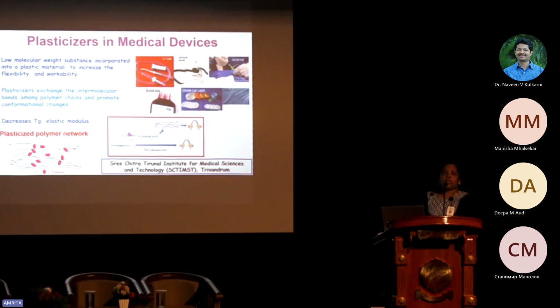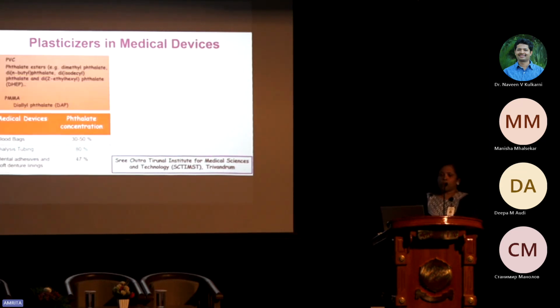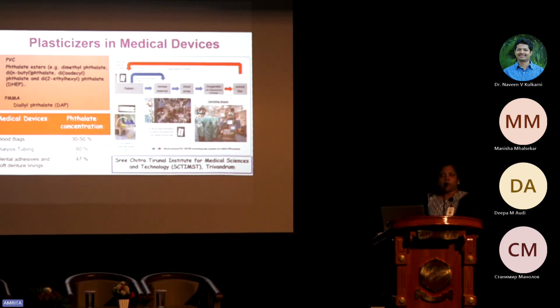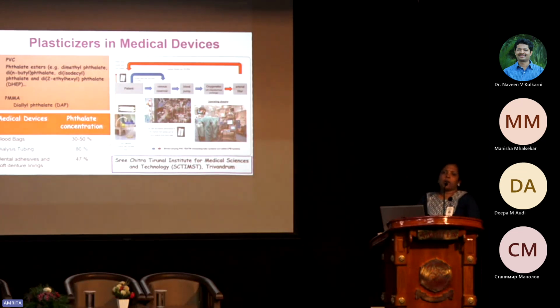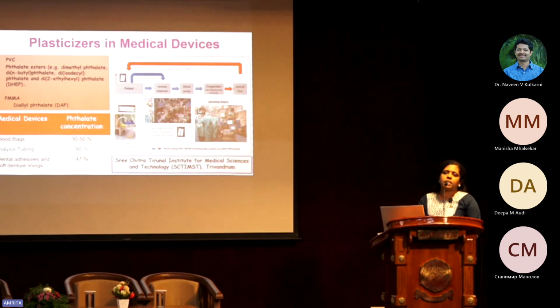So the plasticizers are used in many biomedical devices, including IV tubes, catheters, blood bags, etc., and also in very high concentrations. There are different forms of plasticizers used depending upon the polymer matrix, the parent polymer matrix, and also the application. In PVC, that is polyvinyl chloride, there are different plasticizers, especially phthalate-based plasticizers like dimethyl phthalate and diethyl hexyl phthalate, that is DEHP. In the case of the PMMA matrix, polymethyl methacrylate, there are plasticizers like diallyl phthalate, and in other systems there are many more plasticizers like low molecular weight polyethylene glycol, glycerol, or bioplasticizers like olive oil. There are many plasticizers being used.